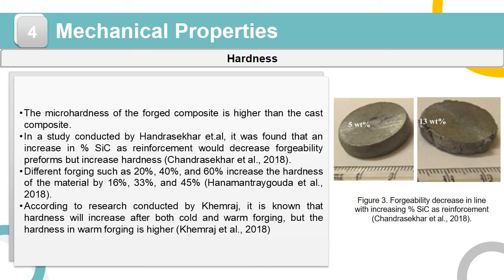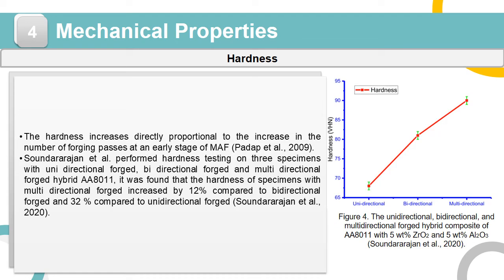Different forging reductions, such as 20%, 40%, and 60%, increase the hardness of the material by 16%, 33%, and 45%. That means hardness increases in line with increasing forging. According to the research conducted by Khemraj, the hardness will increase after both cold and warm forging, but the hardness in warm forging is higher because the deformed material obtains strength from precipitation of coherent particles and dislocation accumulation through forming. The hardness increases directly proportional to the number of forging passes at an early stage of multiaxial forging.